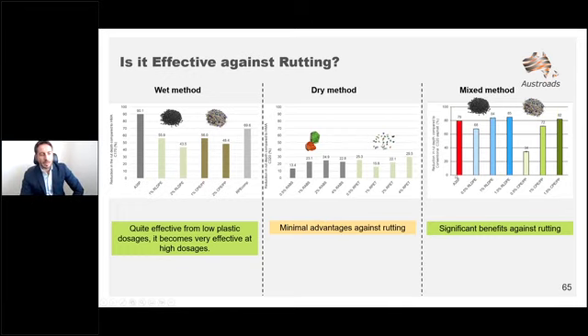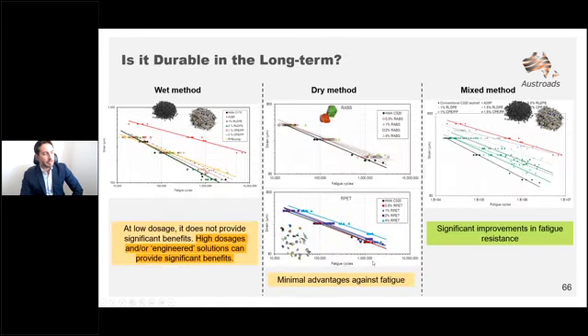The last one is the one we've been discussing today, the mixed method, and this is probably the most promising in terms of usability in the field. There is quite a remarkable effect in terms of rutting, especially if you select the right content and the right type of plastics. We've been talking about 3 out of the 6 mixes performing better than the conventional polymer modified binder used in Australia. Is it durable in the long term?